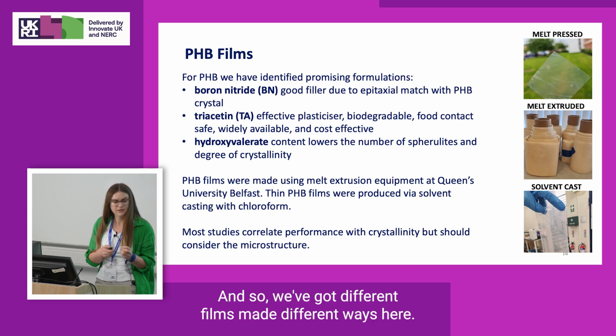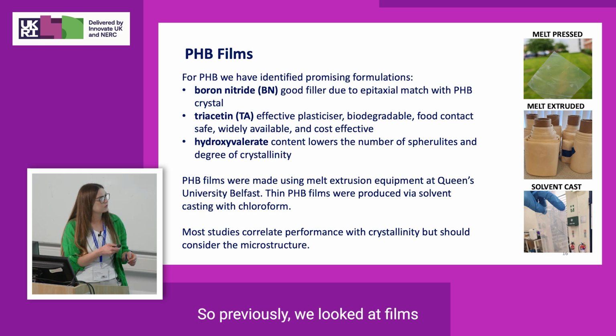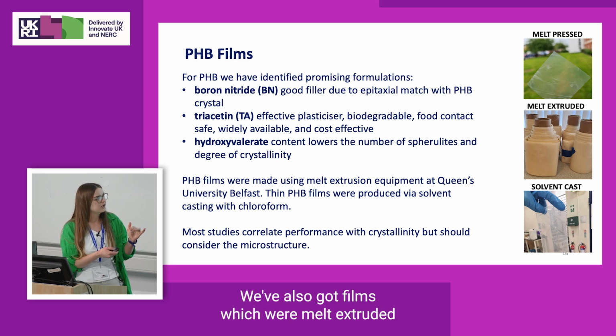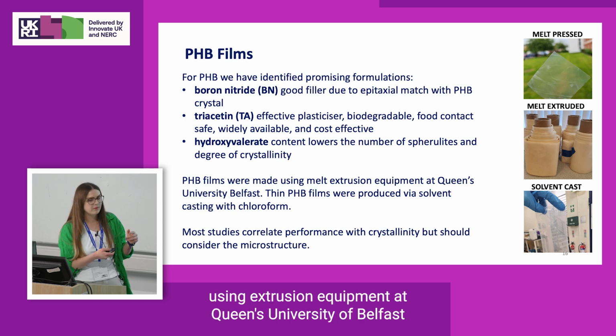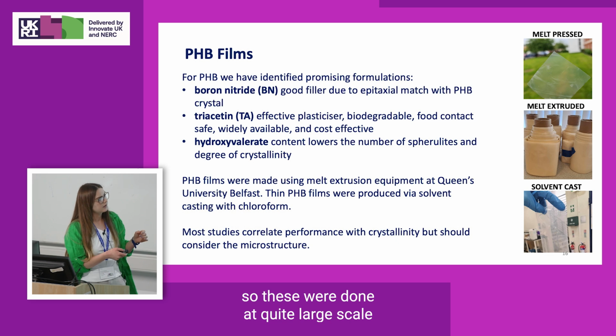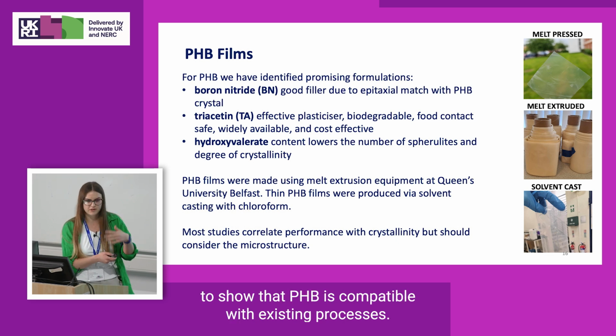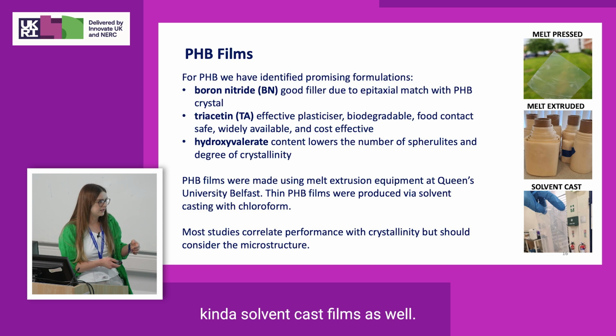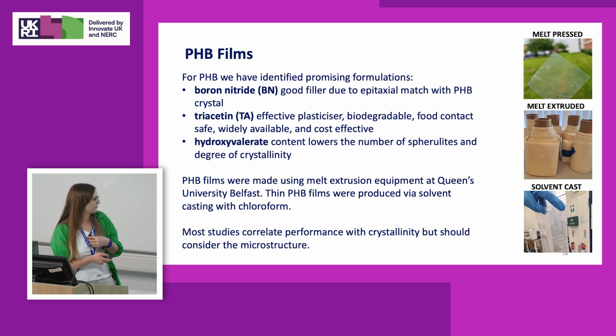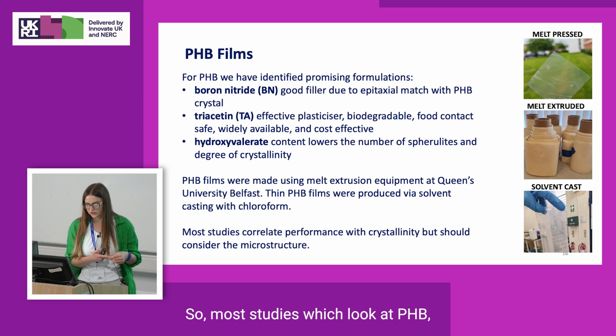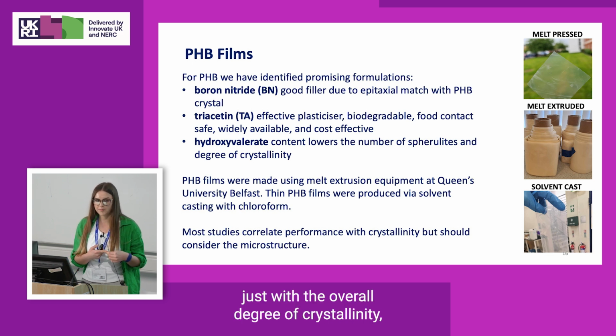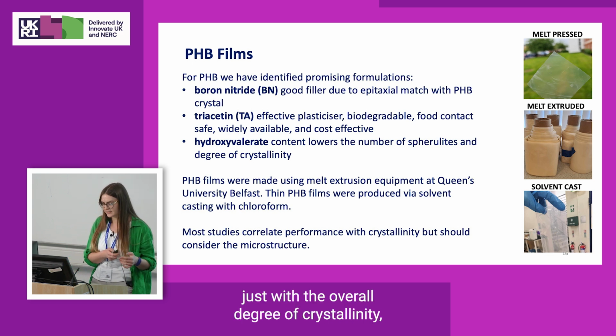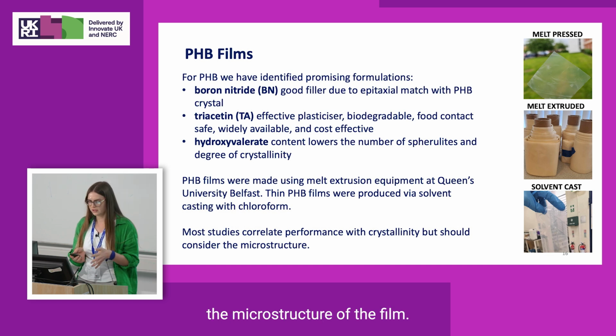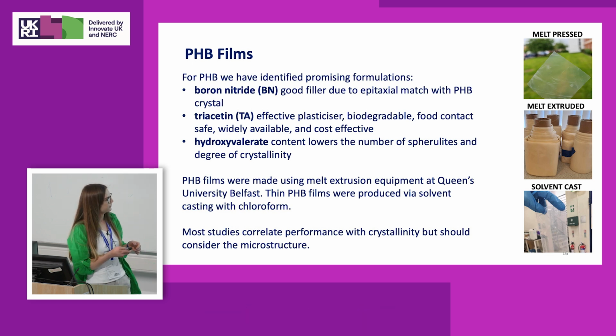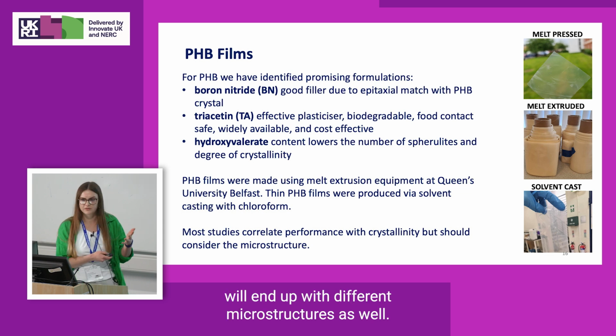And so we've got different films made different ways here. So previously we looked at films that had been melt pressed. We've also got films which were melt extruded using extrusion equipment at Queen's University Belfast. So these were done at quite large scale to show that PHB is compatible with existing processes. And then we've got our thin solvent cast films as well. So most studies which look at PHB correlate its performance just with the overall degree of crystallinity, but very few actually delve into the microstructure of the film. And films produced in different ways will end up with different microstructures as well.